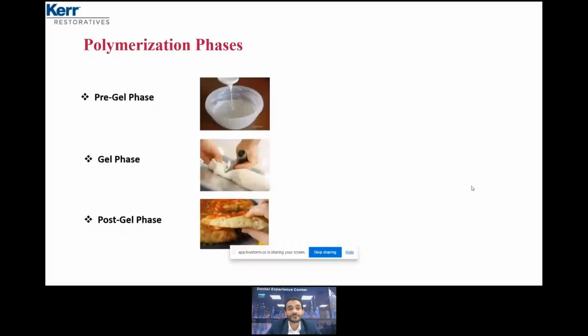Gel phase. If we remove the cement in the gel phase, you will be in a safe way. How can we reach the gel phase? The traditional way for all of us, we can use the light cure for 2, 3, 4 seconds in order to reach the gel phase, according for sure to the manufacturer of the dental cement. So again, trust me, cementation is a delicate step. Success of the restoration can be in the hand of the cement. So it is mandatory to remove the excess only in the gel phase.